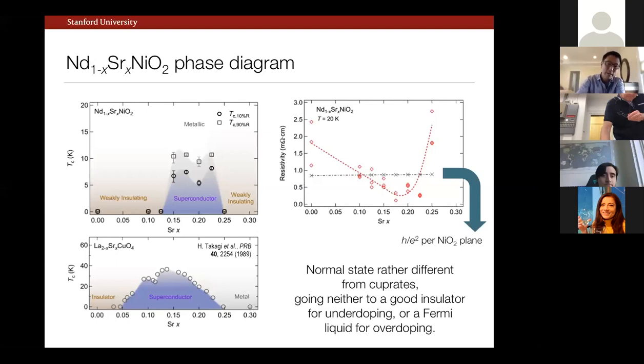But just to set the scale, it's quite suggestive that right here is the only regime where, in the simplified thinking, we were dipping into the regime of having coherent transport. So to give you a scale, k_F l in 2D units here is of order 4 or 5, right? So barely coherent transport. And perhaps it's not a coincidence that only in this maximum conductivity regime do we have precisely the observation of superconductivity. But either side of this is rather distinct, okay? And I'll come back to some thoughts on that, mostly from other groups.